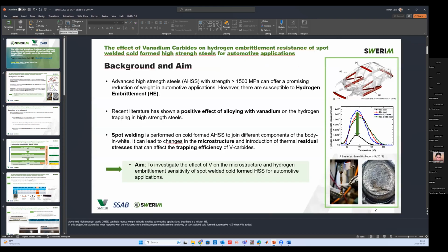So a little bit about the background and the aim of this project. Advanced high strength steels with strength over 1500 megapascal can offer good properties and a reduction in weight in automotive applications, lowering the CO2 emission. However, their sensitive point is that they are susceptible to hydrogen embrittlement. Recent literature points out that alloying with vanadium could give effective trapping of hydrogen in high-strength steels, providing the possibility to mitigate hydrogen embrittlement.